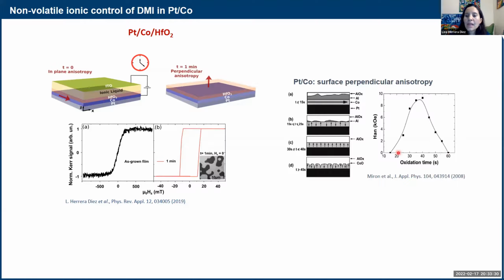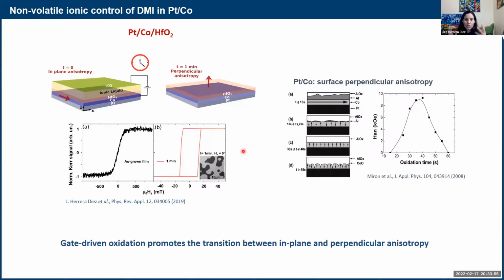So this curve is very important for Magnetoionics because this is basically what we do with the oxygen, right? We start at some point in this curve, and then we just add more oxygen or we come back. So we knew very well that this meant that we started off with a layer that was under oxidized, and then we just went all the way up to PMA. So we could see that we could drive this transition between in-plane and out-of-plane with the gate, thanks to this controlled oxidation of the interface.